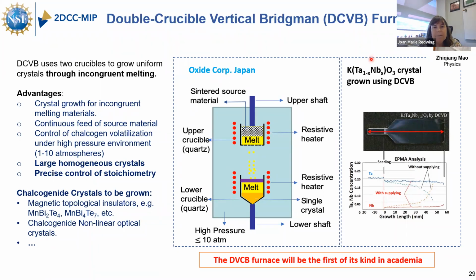So to get around that problem, this system is going to have a second crucible that can continuously supply a source material into the growth crucible. And that enables active control of the melt composition. And this will provide a way to more precisely control the crystal stoichiometry, as well as producing much larger homogeneous crystals. In addition, this system is going to be capable of operating at pressures up to 10 atmospheres. And that's important for chalcogenides because you can have significant loss of the volatile chalcogen species from the melt at high temperature. So this particular technique was developed by Oxide Corporation.